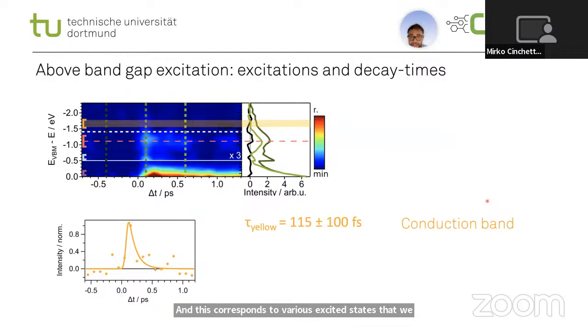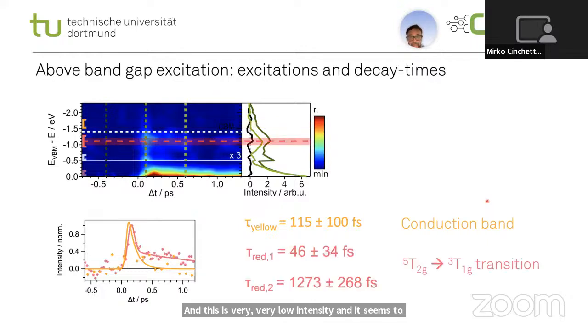The first state that we see is the conduction band. This is very low intensity, and it seems to decay very fast, which we do not fully understand. Then we have a signal at 1.1 electron volt above the valence band maximum. And by using the same argumentation that I showed you before, we can ascribe it to the second DD transition. So this is the spin non-conserving transition from 5 to 3. And you see that the time evolution is non-monotonic, it has at least 2 exponents. We can fit this with a double exponential decay, and we find 2 time constants. One is 50 femtoseconds and one is 1200 femtoseconds.